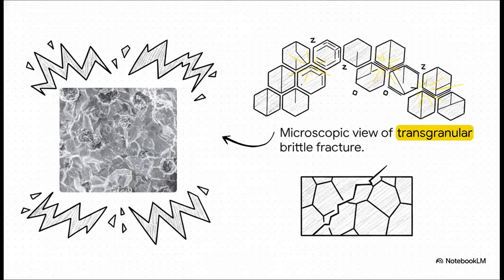Now, when we zoom in on that brittle material with our electron microscope, we see something called transgranular fracture, or cleavage. The crack propagation here is so incredibly rapid and unstable that it literally just snaps the atomic bonds and slices straight through the material's structural grains. That's what creates this flat, faceted, almost rock-like texture you're seeing here.